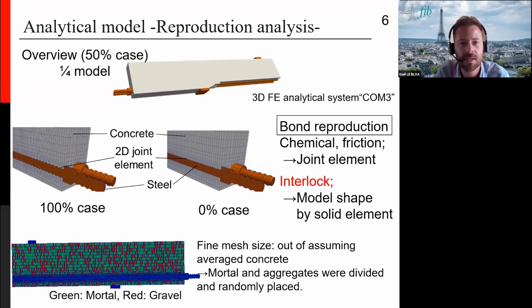I have a question. In your test setup for the 50% interlock case, you chose a reduction of the concrete cross section. How can this influence the overall resistance behavior of the beam, especially as you mentioned that there is shear failure of this portion? Did you also observe an uplift effect from the fact that there is no concrete cover? And why did you not choose to have a rebar with a lug on the top and a round bar on the bottom?